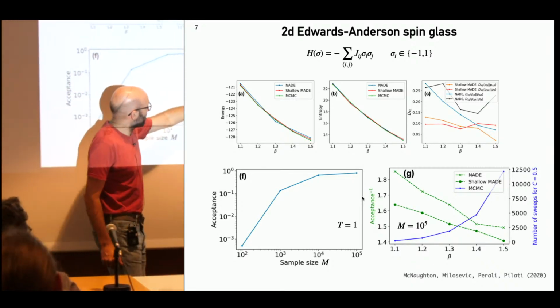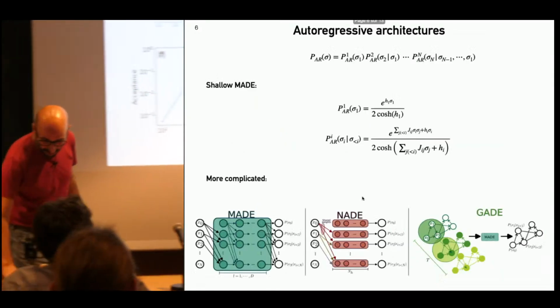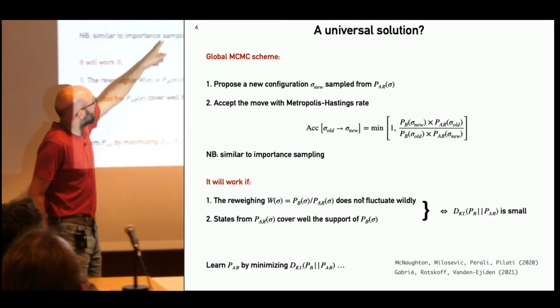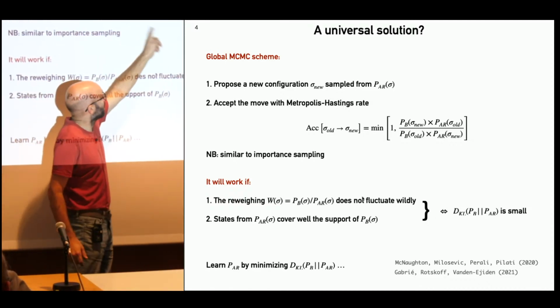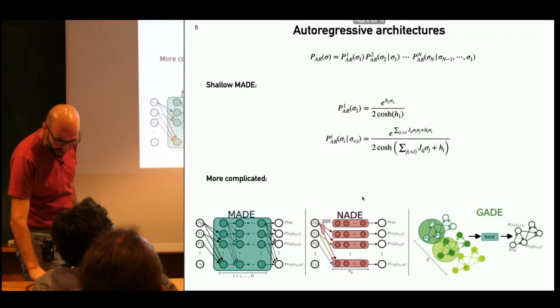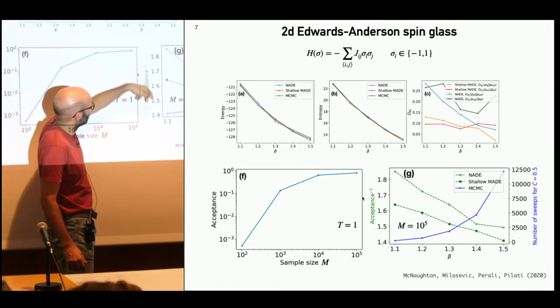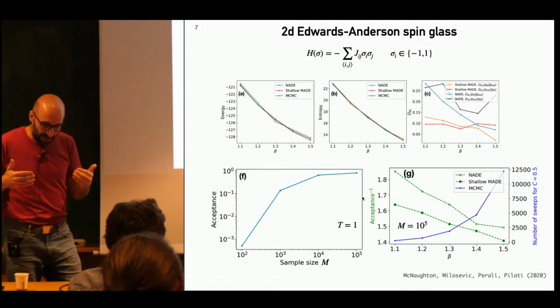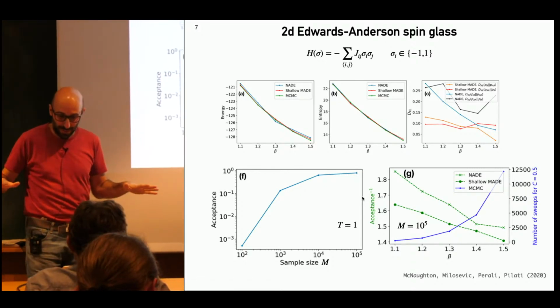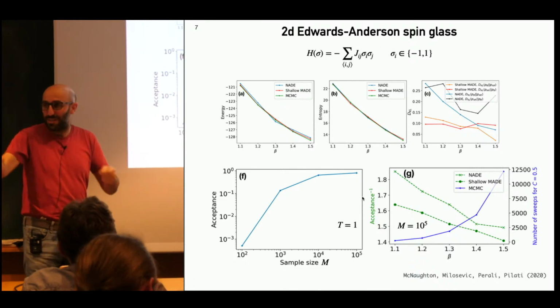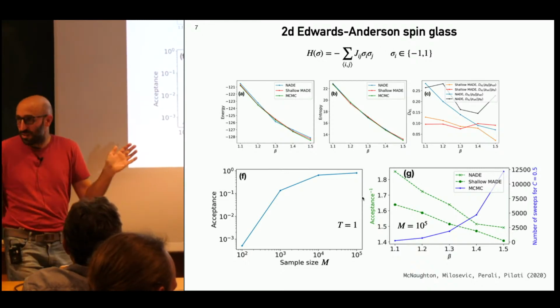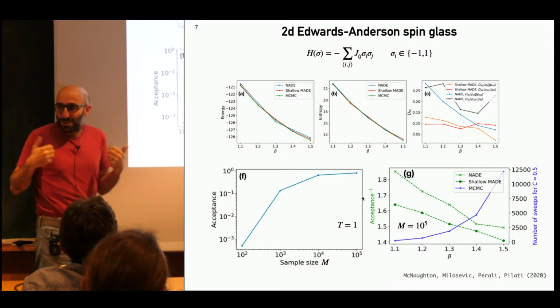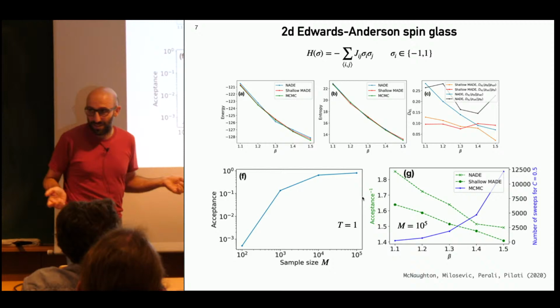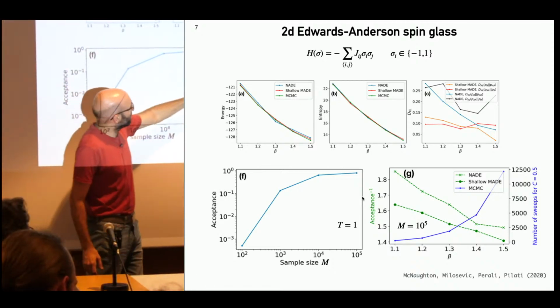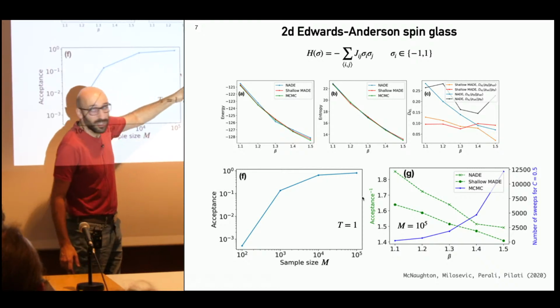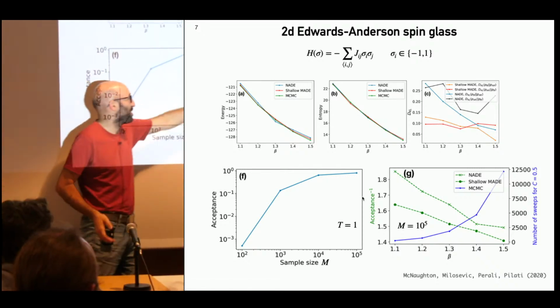And indeed, you can see the acceptance rate. When I do the global Monte Carlo, I propose moves from the model that I learned, and then I accept with this probability. This is the average of this acceptance probability, the inverse, because the autoregressive model is spread over the whole phase space, so when you propose a new configuration, it's going to be essentially uncorrelated from the previous one. So if you accept the move, you are basically decorrelated. The relaxation time of the global MCMC is basically the inverse of the acceptance rate. That's why we plot the inverse, and this is the right scale to look at. It's of order 1. So you accept one move every 1.5.